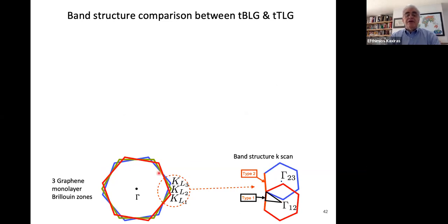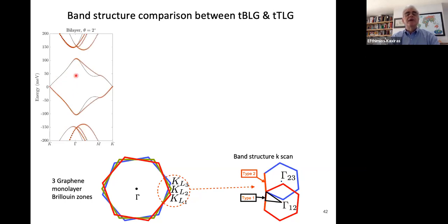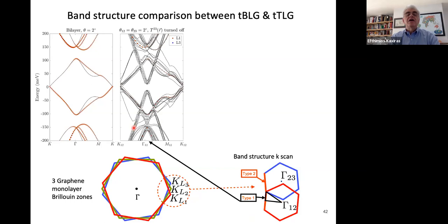So here are the three Brillouin zones associated with the three different layers twisted relative to each other. And this is the supercell structure. And you can scan now this K-space in different directions. This is what we call a type 1 scan along this triangle, or type 2 scan along these two sides of the Brillouin zones of the individual pairs. So this is the Brillouin zone of pair 1, 2, and this is the Brillouin zone of pair 2, 3, the supercell Brillouin zones. So here for reference is the twisted bilayer result at 2 degrees. The bands are not flat here. So then I'll show you a scan around this area. So here it is. And you see essentially the twisted bilayer bands and an additional Dirac cone. This is with the interaction between layers 2 and 3 turned off.